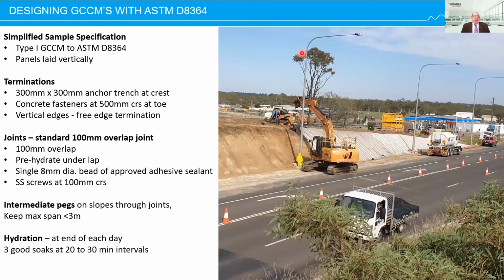So a typical sample specification for a slope protection job like this would be type 1 GCCM, panels laid vertically, 300 by 300 millimeter anchor trench at the crest, 500 mm centers, concrete fasteners at the toe. The vertical edges were treated with free edge termination, which I discussed earlier. The joints were the standard overlap joints, screws at 100 mm centers, and intermediate pegs on slopes were used to keep maximum span less than 3 meters to prevent shrinkage. And the hydration specification was 3 good soaks at 20 to 30 minute intervals.